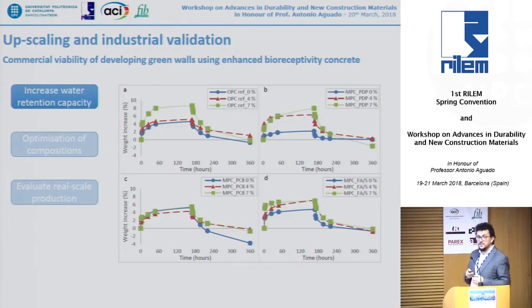In order to increase the water retention capacity, this morning we had a very nice talk on the use of superabsorbent polymers. We are also evaluating the use of these superabsorbent polymers in order to have a water retention reservoir inside our material. So any water that comes in from the exterior is retained for the longest time possible to allow biological colonization and biological growth on the surface. We evaluate different sets of samples with varying percentages of superabsorbent polymers in order to evaluate the weight increase, and also the loss of this water, with very simple tests.